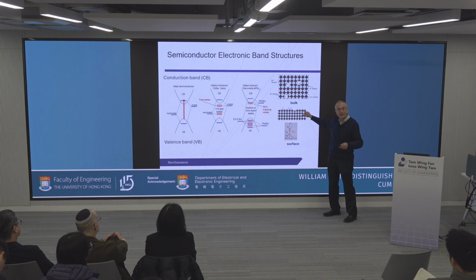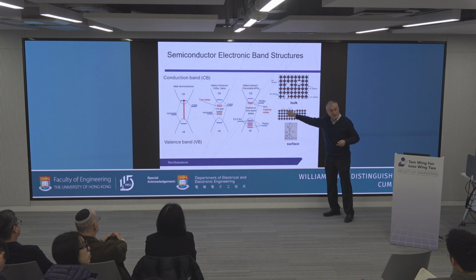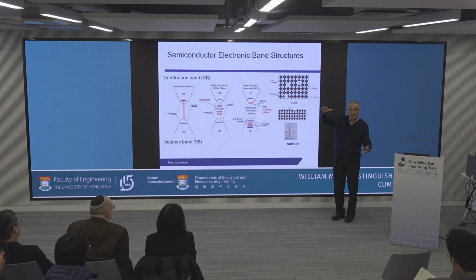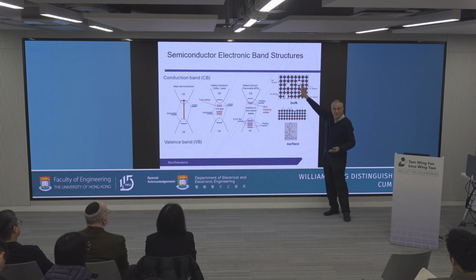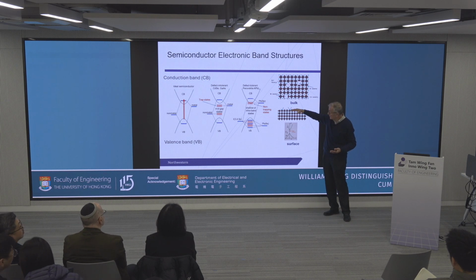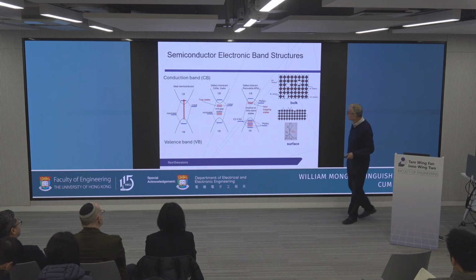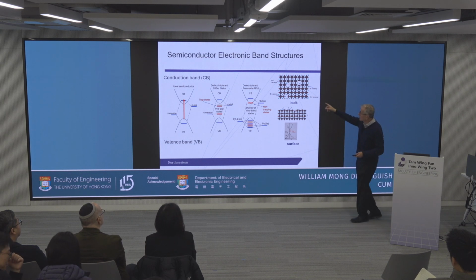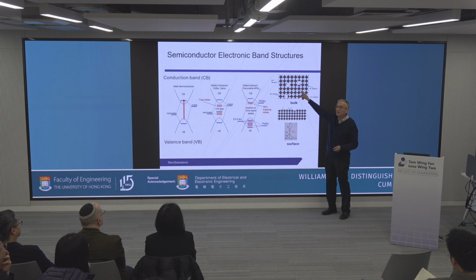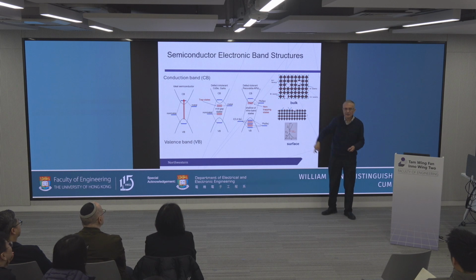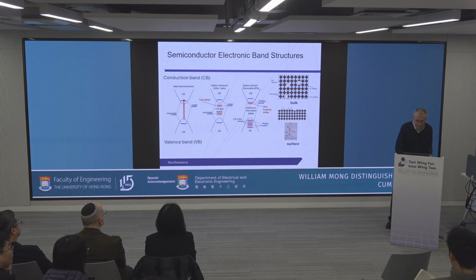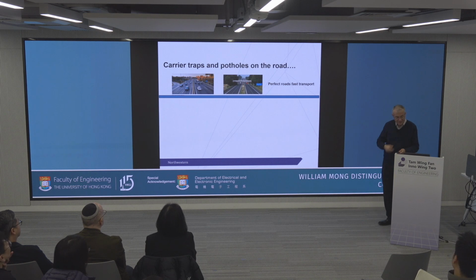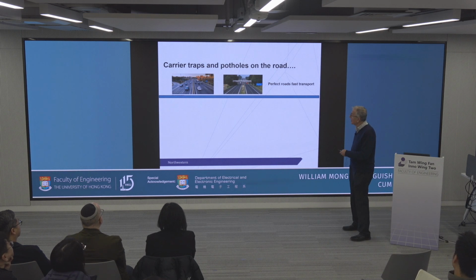If you want to get the extra percent from 20, 21 to 25, 26, 27, you need to fix the surface. So the heavy lifting is still being done by the defect-tolerant lattice, but the extra has to be obtained by fixing the surface. And that's why these things were not supposed to work. Nobody was excited because they were disordered. They were dynamic and disordered, but they do work. So here's my analogy.